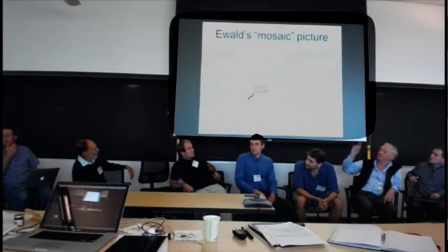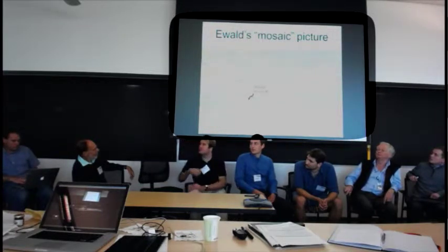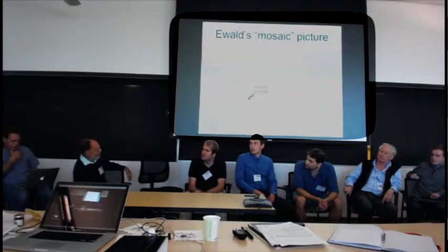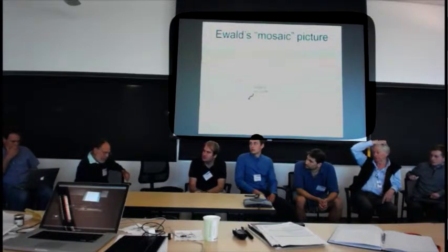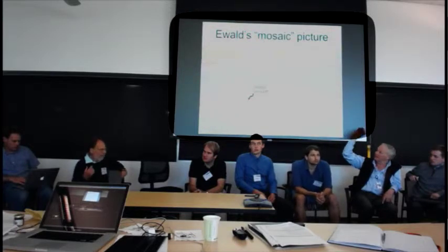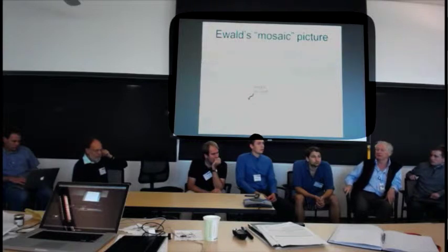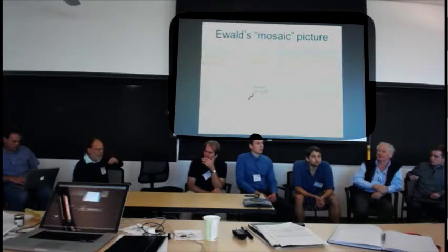Well, what is the cryo image? Well, yeah, you can have grain boundaries. Low angle grain boundaries. But if you're within the coherence length, then all you're doing is creating a distribution of atomic displacements by rotating a block. Yeah. And if this is an inorganic crystal, there would have to be a low angle grain boundary consisting of a line of dislocations. So the question is, have the dislocations been seen?